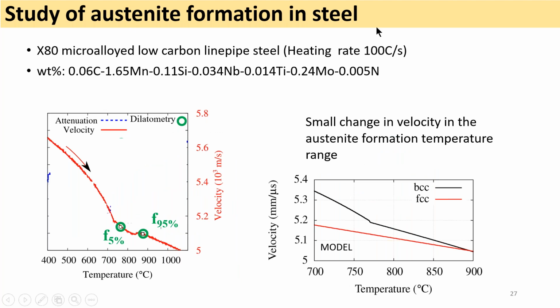Okay, so remaining with steels, I'd like now to talk about the speed of sound, the velocity, and how this looks. As we raise the temperature in steel, the speed of sound decreases non-linearly because of the magnetic property of the ferrite phase, BCC, up until a discontinuity here, which is the Curie temperature. What we see here is the moment where the fraction of austenite starts to rise. Here is 5% of austenite, and here by dilatometry we could see it's 95% of austenite.